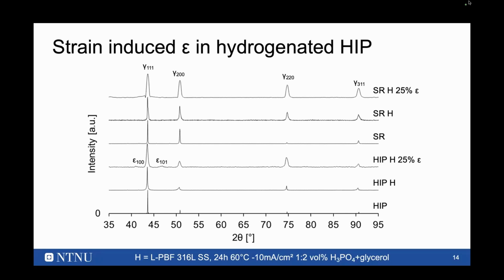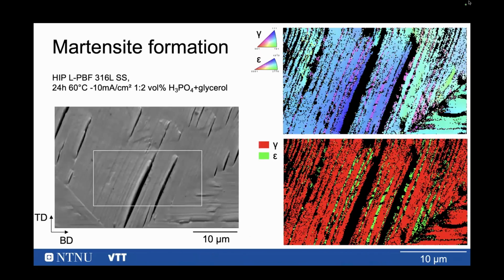So we did XRD, and of course we compared three conditions: first the one in air, then with hydrogen charging before the tensile testing, and then with hydrogen charging after 25% straining. We see mainly austenite present. The peak becomes broader, which is expected because hydrogen is inducing strain, and the deformation will broaden the peaks even more. But interesting here is that in the case of HIP, after deformation, we see some epsilon martensite present. This observation was also confirmed by EBSD.